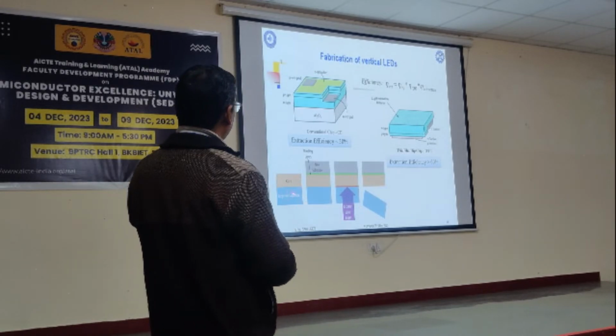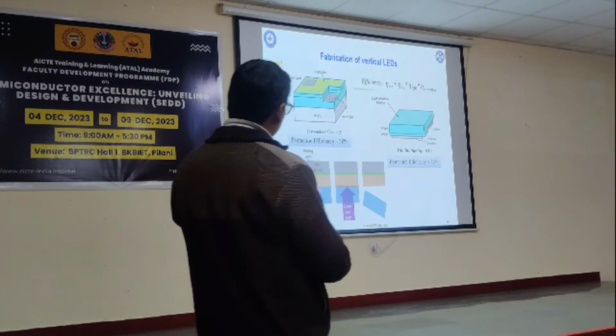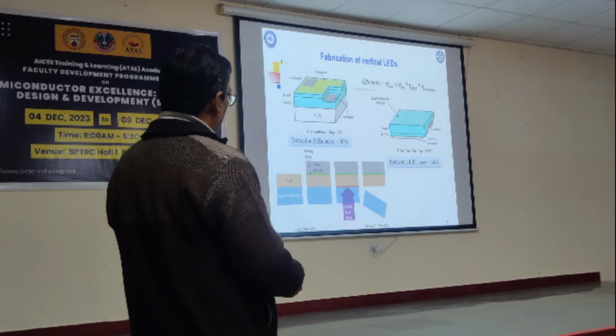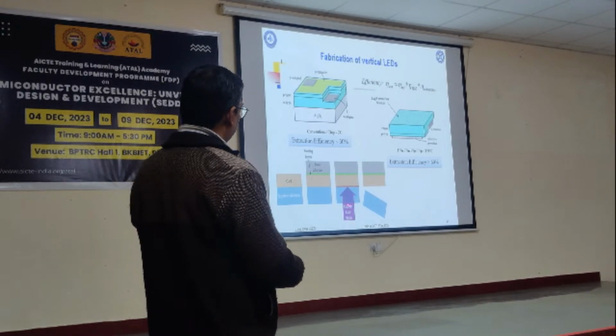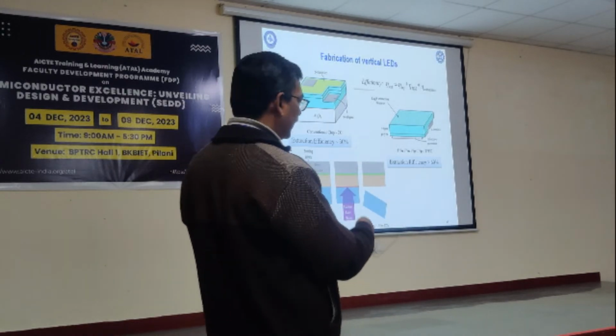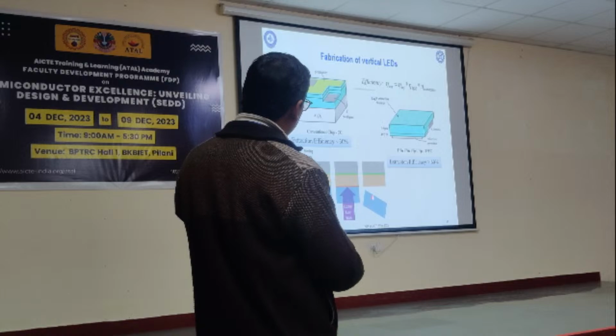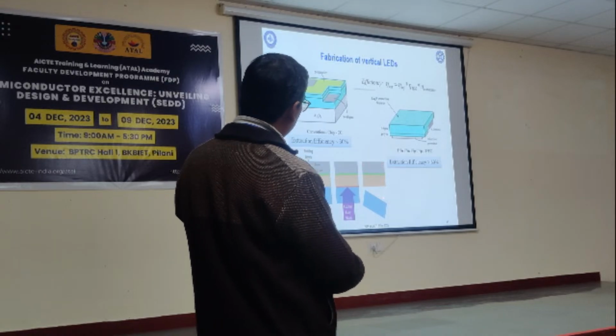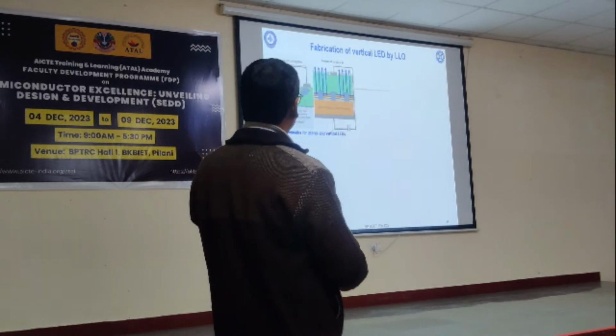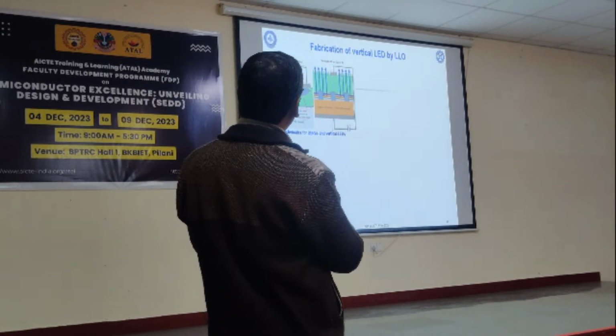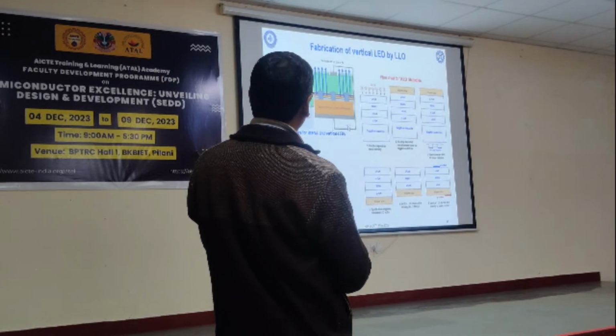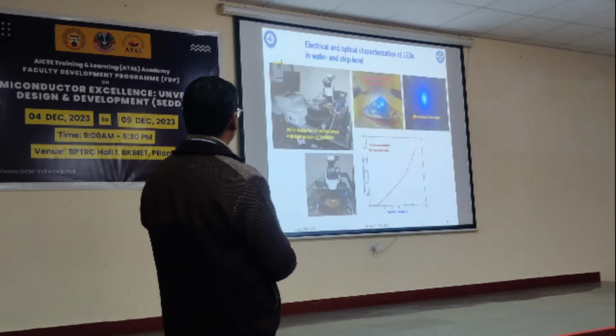The other point is the vertical LED formation, where gallium nitride will be grown on top of a sapphire substrate. After growth of that material, we use laser light to break the interface between gallium nitride and sapphire, because the excimer laser that we are using is transparent in sapphire but is absorbed in the gallium nitride material. At the interface, gallium nitride will form gallium metal and nitrogen gas. That will break after certain chemical treatment. So the sapphire substrate will be removed, a new substrate is there, and we will fabricate the device on the other side. In that case, in the vertical LED the current will flow in the vertical direction, and there will be much more light output. The LED can be operated at very high power. Those are a few examples of what we have.